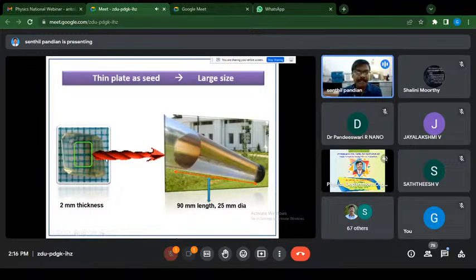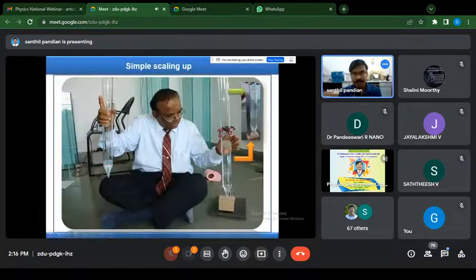So with a thin plate seed crystal, this much large size crystal is possible by this SR method. You see, from a very thin plate, you are able to grow nearly 9 centimeter long and 2.5 centimeter diameter SSD single crystal for the SHG application. The scaling up was relatively very simple by this method, and he is Professor P. Ramasamy. He was my PhD supervisor. He is also the director and dean of the SSN institution, and he is holding these benzophenone organic single crystals for SHG application.